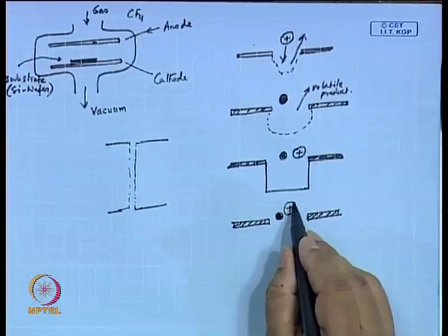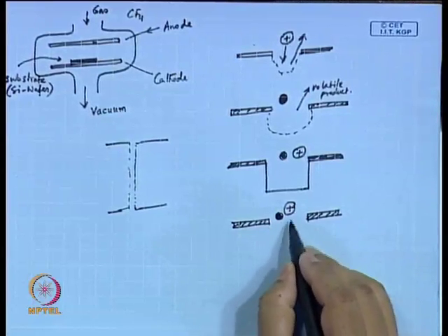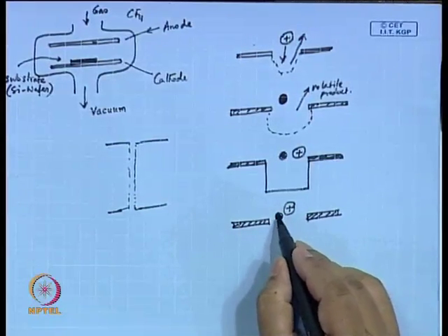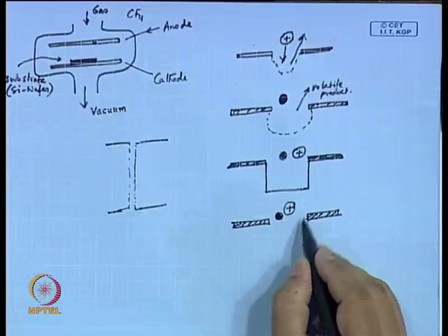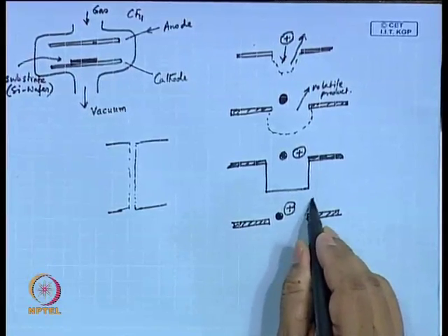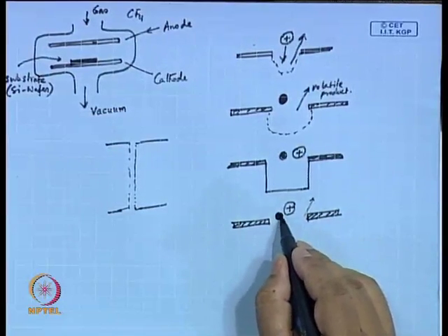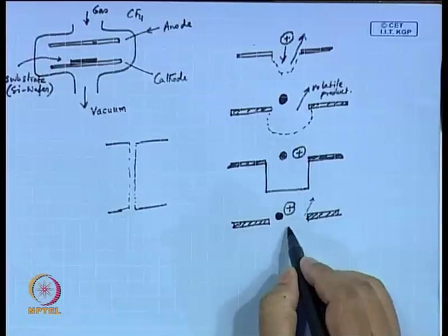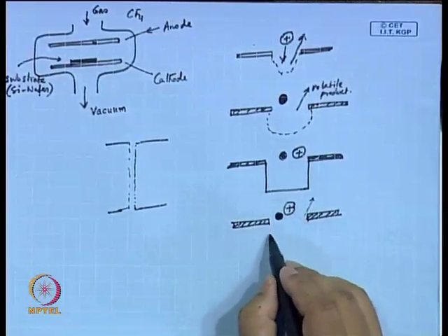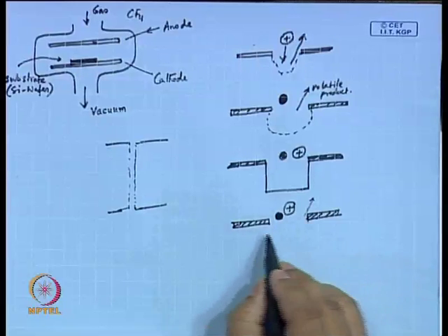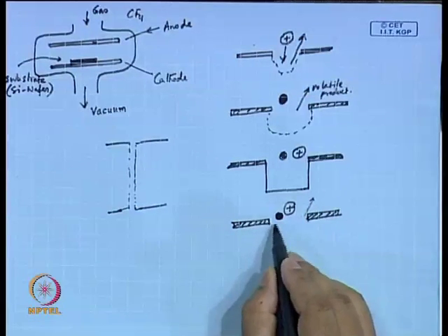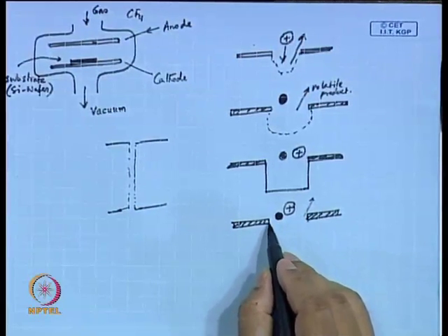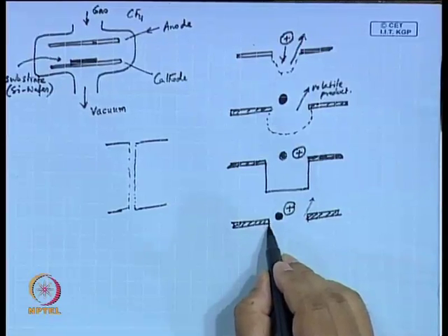Now, the ion, whichever is reflected, will go out. However, the chemical entity, the product that is formed, is not diffusing out; rather, it is a non-volatile product. So, what will happen is that it will stick to the surface.